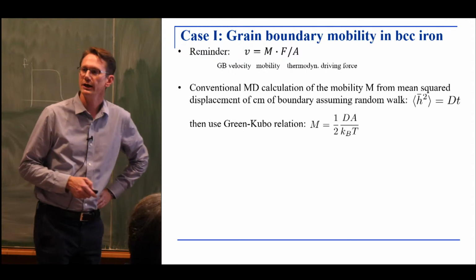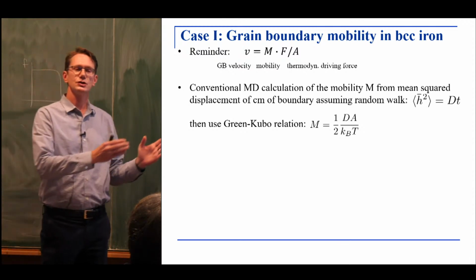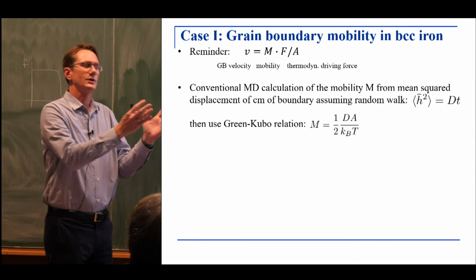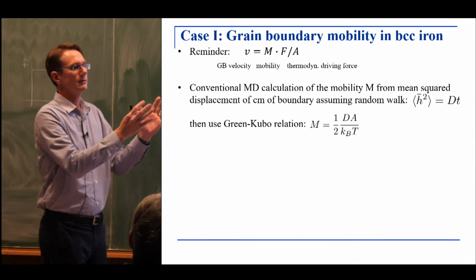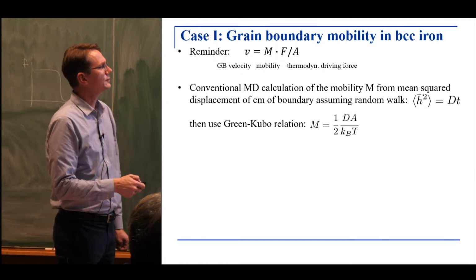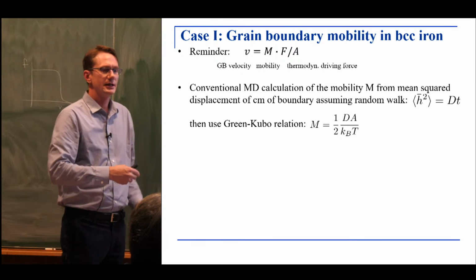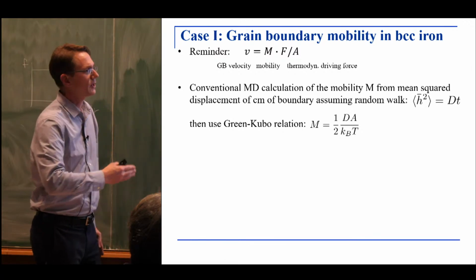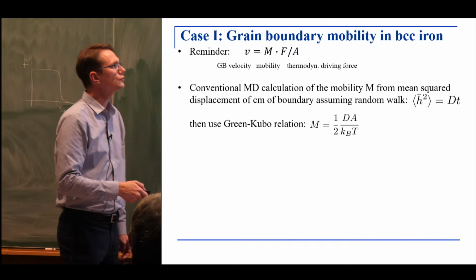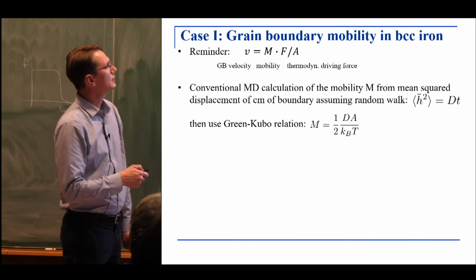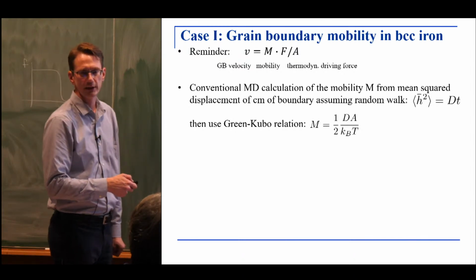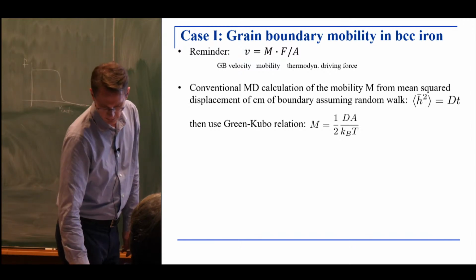In a conventional molecular dynamics calculation, you would just run this boundary at finite temperature, let it fluctuate, and measure its mean squared displacement. If this is linear, which is the typical thing to expect, then the boundary is just diffusing. You can extract the diffusion constant, D, and using a Green-Kubo relation, you can convert that into a mobility.